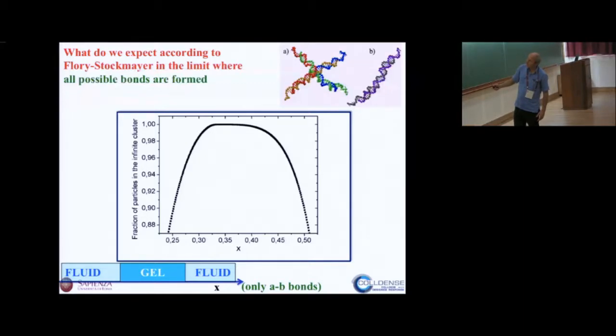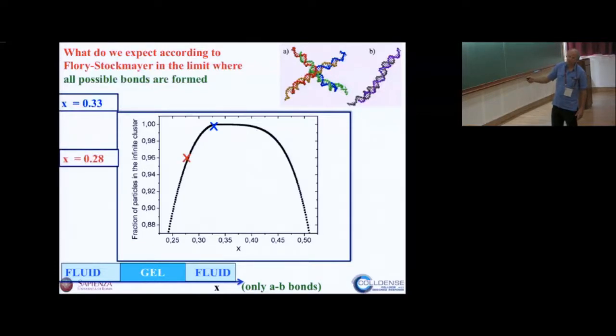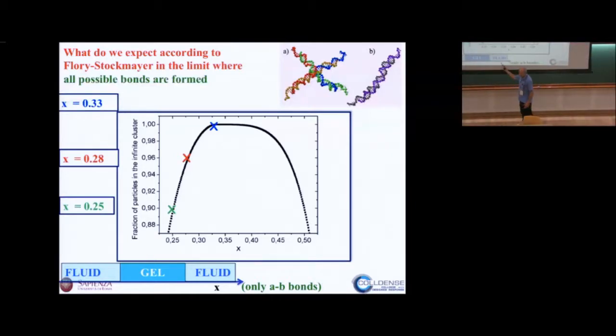And you see here that if you work at the stoichiometric ratio, then all particles are in the infinite network, and this is calculated assuming that all possible bonds are formed, really in the ground state. So you work with the ratio 0.33, and of course all particles are in the infinite network. But if you go down to 0.28, then 96% of the particles are in the infinite network. And then if you work with X 0.25, then 90% of the particles are in the infinite network. So those typical numbers give us a reasonable number of free ends, but still we have a strong network that can support stress. So essentially, what we are trying to do is, again, fluid, gel, fluid, but this time playing with the concentration, X.